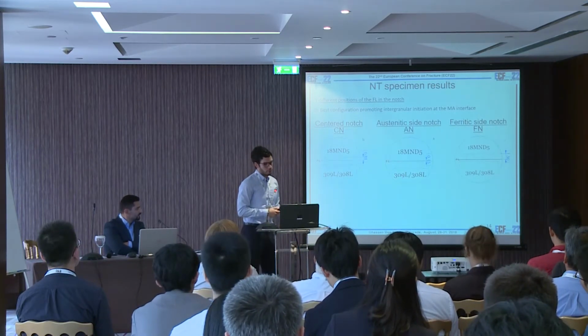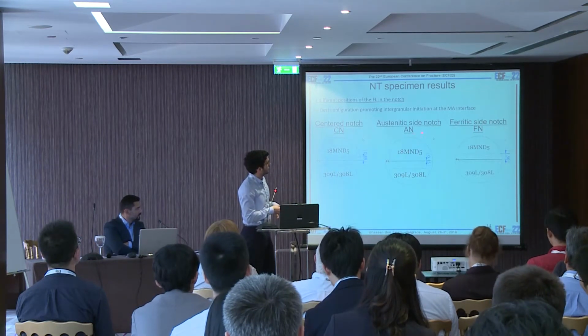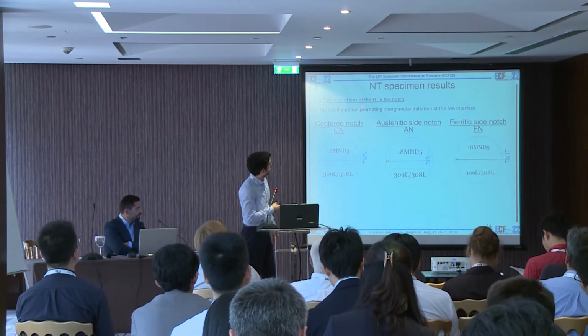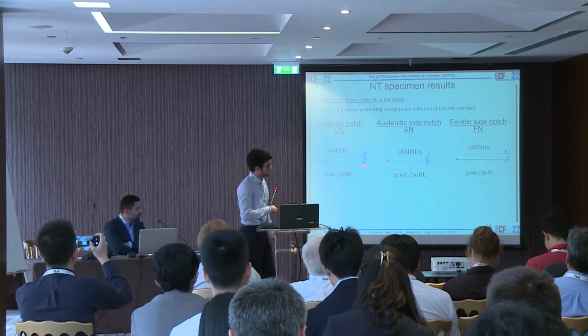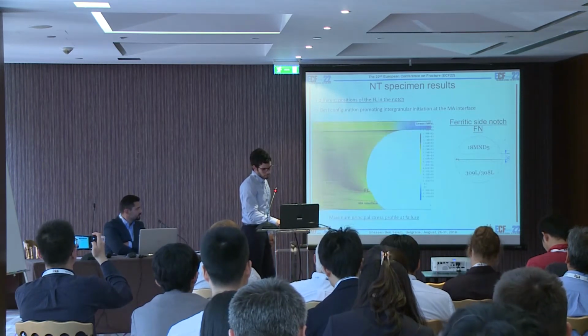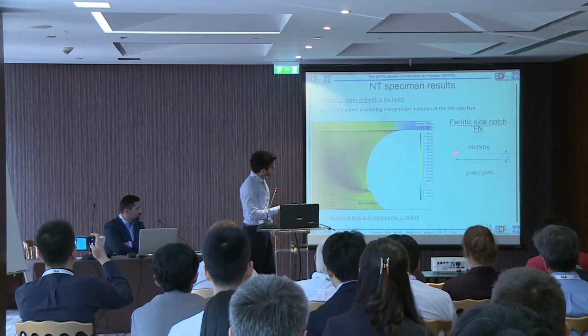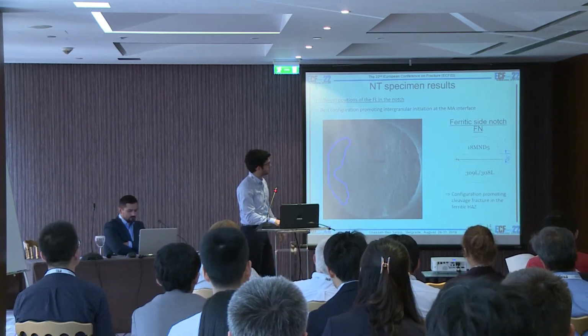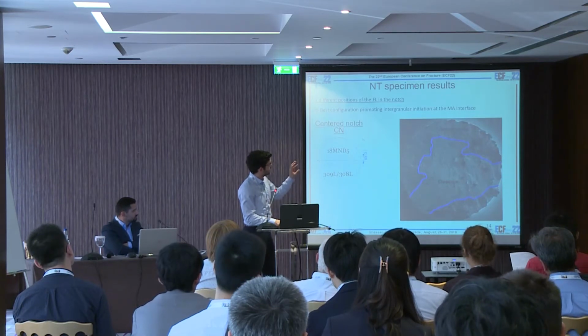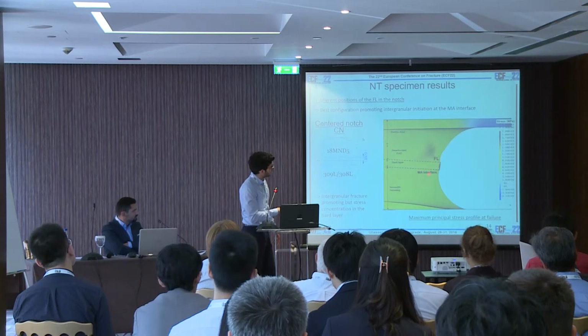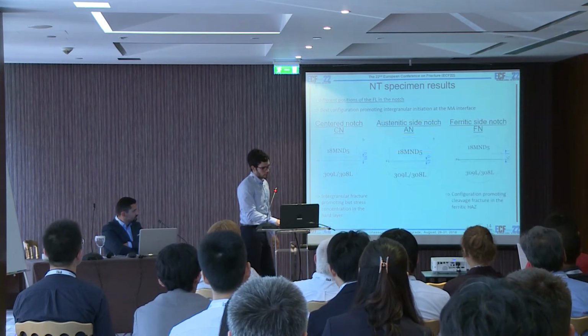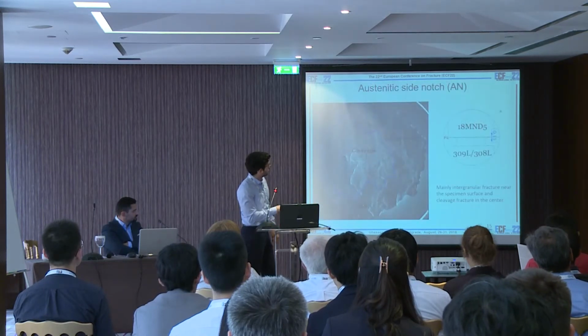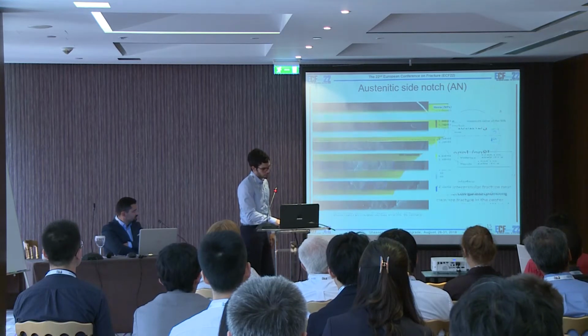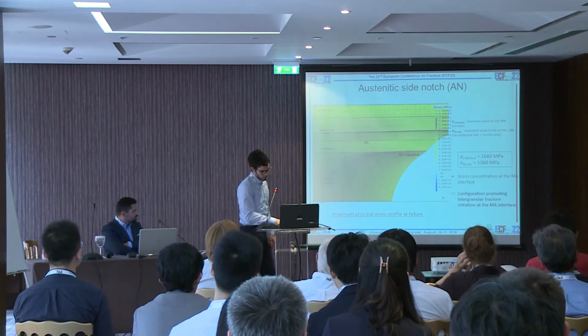So to choose the best configuration promoting intergranular initiation, we tested 3 different positions of the hard layer in the notch. So these are the 3 configurations. The first one concentrates stresses in the ferritic HAZ, so seems to promote cleavage fracture in the ferritic HAZ. So it's not suitable, as we can see here. So very limited intergranular fracture. The second one seems to promote intergranular fracture, but concentrates stresses in the hard layer and not in the MA interface. So as you can guess, we chose the last configuration, which seems to promote intergranular fracture in the specimen boundary and concentrates stresses in the MA interface.